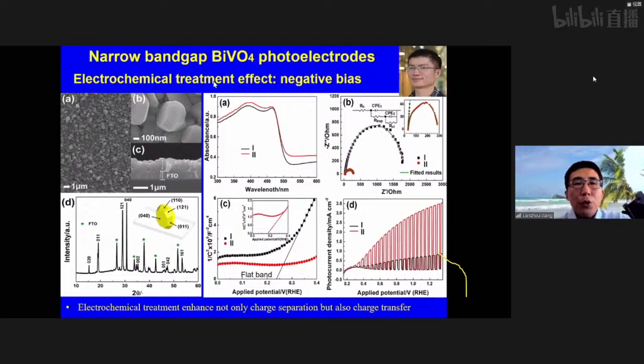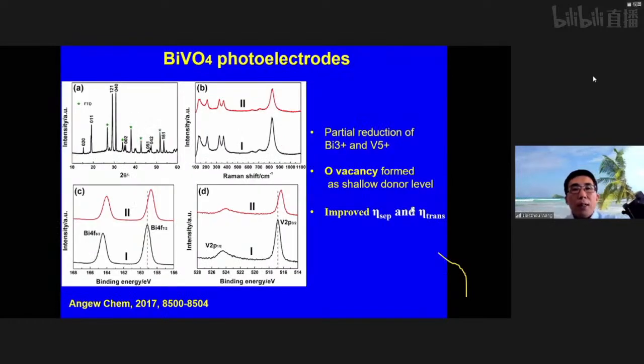Upon the electrochemical treatment of the electrode, we can see a very significant photocurrent increase, going up to around 3 milliampere per square centimeter in this case. We also tried to understand why such electrochemical treatment can increase the photocurrent. Basically, we found the electrochemical treatment partially reduced the transition metal.